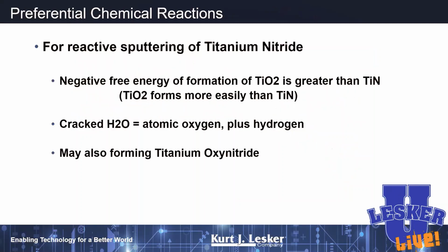So if you're trying to make a titanium nitride, for example, and you've got a lot of water in your system, the negative free energy of formation prefers titanium oxide over titanium nitride. And so if you have a lot of oxygen or a lot of water in your system, you're going to tend to form maybe things like titanium oxynitride. Maybe you'll get a mixture of these things.